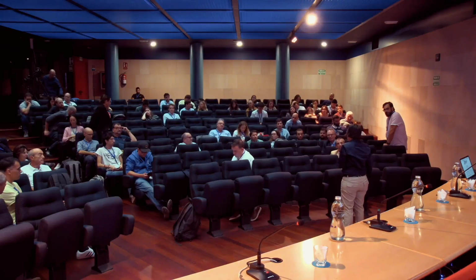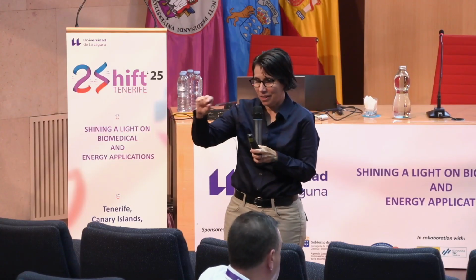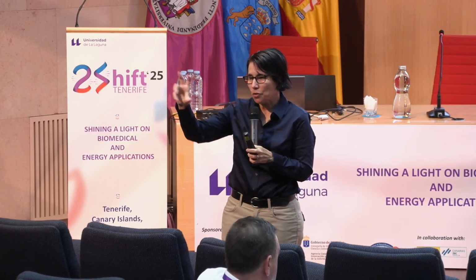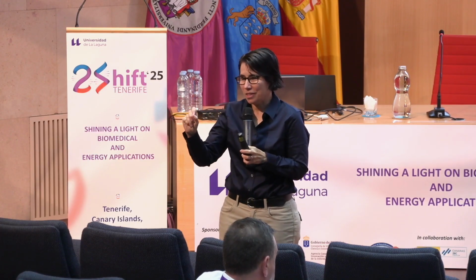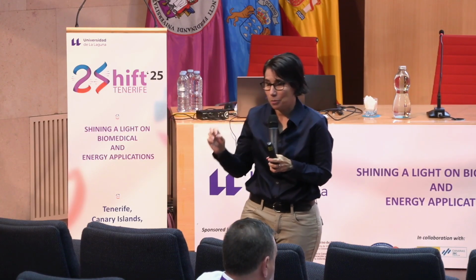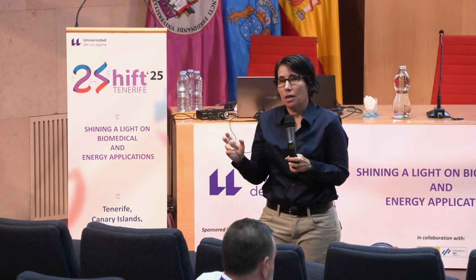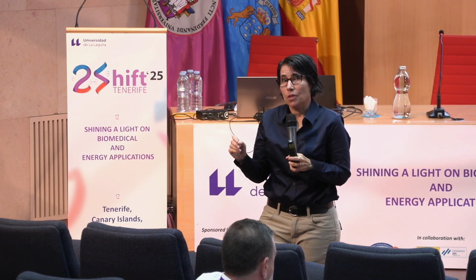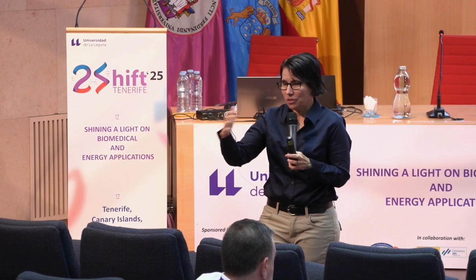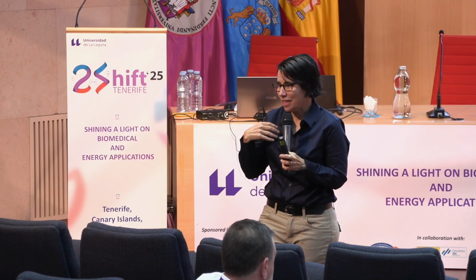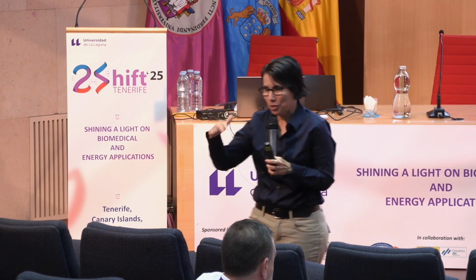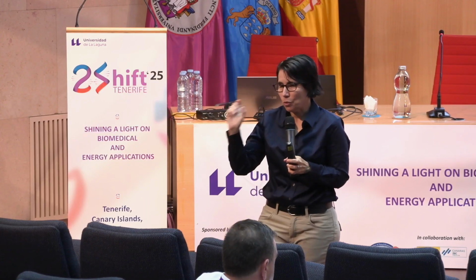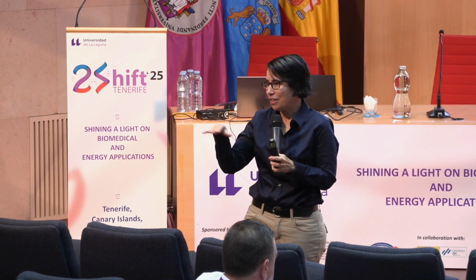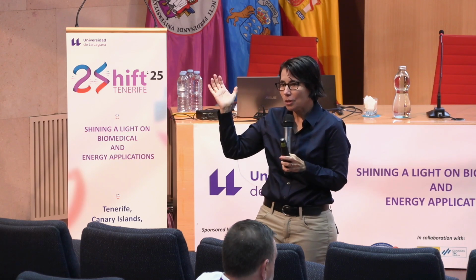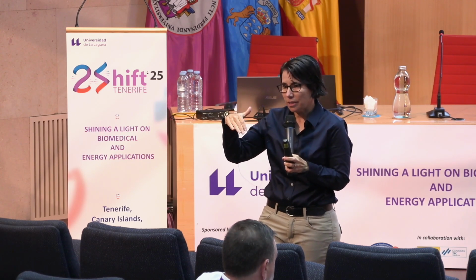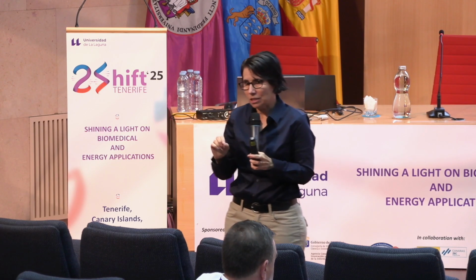So we have to make sure they have some adhesion to the surface. When we put gold nanocrystals on gold, you can imagine that when we do the ligand exchange, you probably get some okay bonding to them. Let me give you an example first: we carefully select the surface so they don't delaminate and we don't lose them. We also put self-assembled monolayers on them so that we don't lose the particles when we do the process.